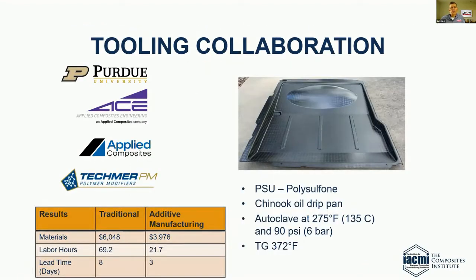Another interesting material is PSU, or polysulfone, with carbon fiber. That was first used in a collaboration between Purdue University, Applied Composites Engineering, or ACE, and their parent company, Applied Composites, and Techmer PM. What they made is a drip pan for a Chinook helicopter. It was put in an autoclave at 275 degrees Fahrenheit, 90 PSI, and came out with a really nice part. The feedback from that is that the traditional tool took $6,000 worth of material, while the additive manufacturing tool was less than $4,000.